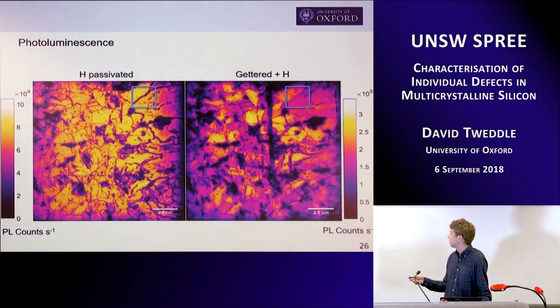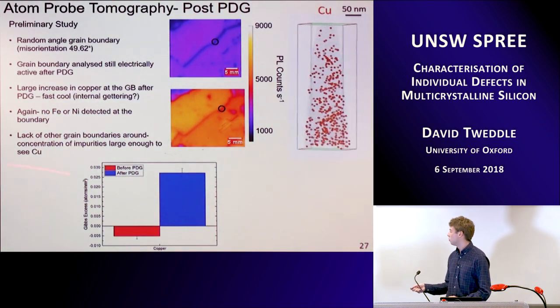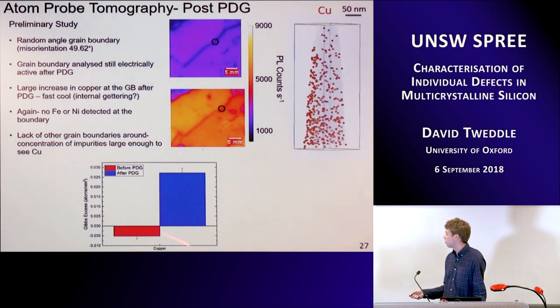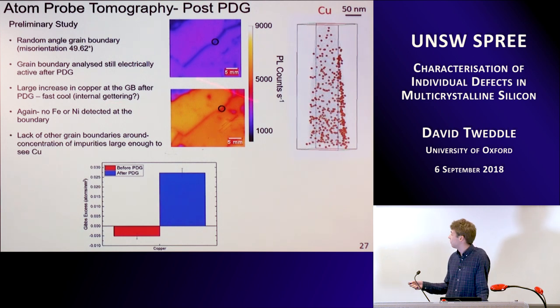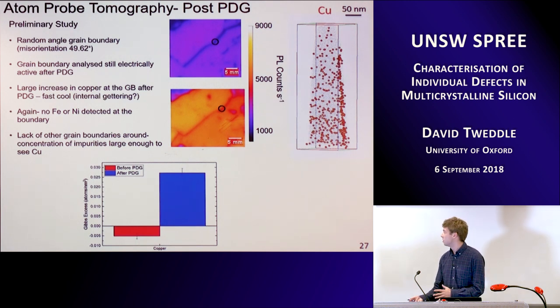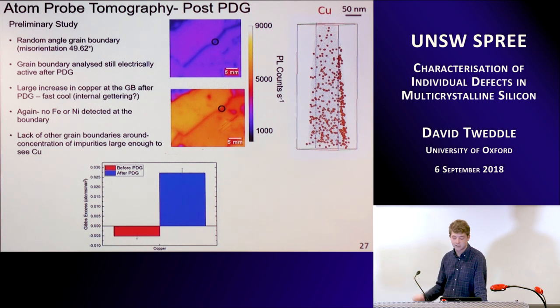Perhaps when we have all these low-angle grain boundaries, there are a lot of places impurities can go and therefore we don't detect the transition metals above our detection limit. However, when we go to a grain boundary that is basically on its own and we still get this increase in recombination after gettering, we can see in the as-cast sample practically zero copper at the grain boundary, whereas after gettering we've got a significant level of copper decorating this grain boundary. So copper may be one of the dominant impurities causing this increase in recombination after gettering. There's no iron or nickel at this boundary, and with a lack of other grain boundaries around, the levels are high enough for us to detect copper.